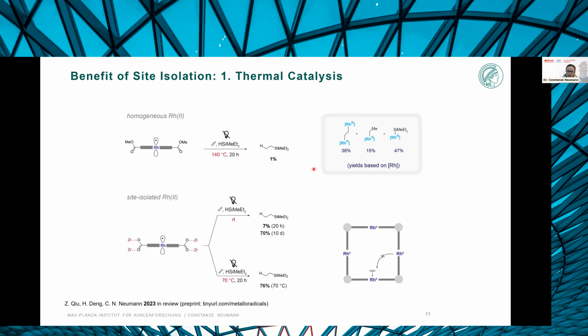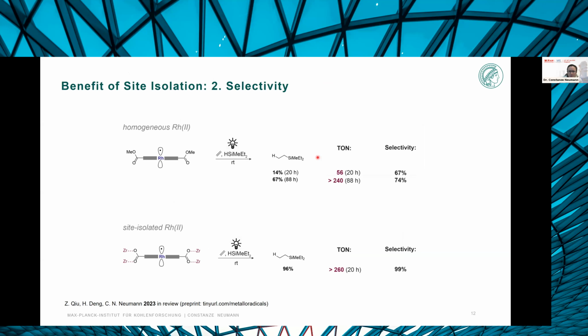And the vast majority of the catalyst actually gets converted into these rhodium-3 intermediates via transformations that are kinetically very facile and sufficiently thermodynamically favorable that even at 140 degrees, the free catalyst is not regenerated, so that the thermal catalysis of this reaction is essentially restricted to the MOF system, and the MOF is truly necessary in order to get this catalysis to work and not simply beneficial for it.